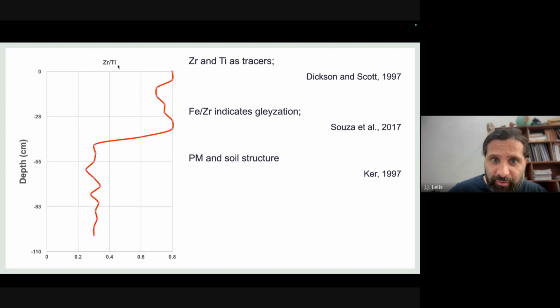Zirconium and titanium are used as tracers of parent material because they cannot be easily leached. Okay, so chemical weathering cannot alter the zirconium and titanium contents in the soil. So if you have a difference of zirconium and titanium contents in the soil, it's because you have a change of parent material, not a change of chemical composition related to parent material or related to chemical weathering.